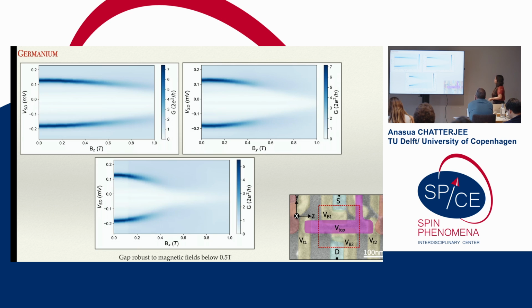The other encouraging thing is that in the center patch, you have a critical magnetic field of up to a Tesla, and we'll see this is repeated also in the other patch. And then the in-plane fields are a bit lower, about 0.5 Tesla.